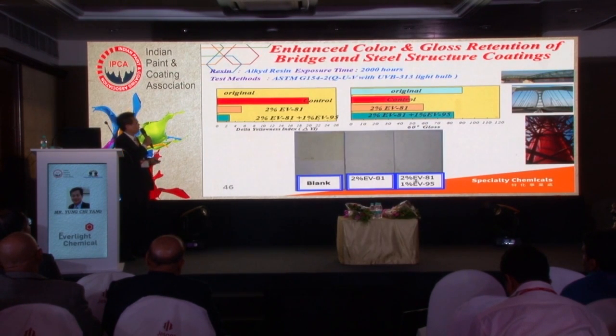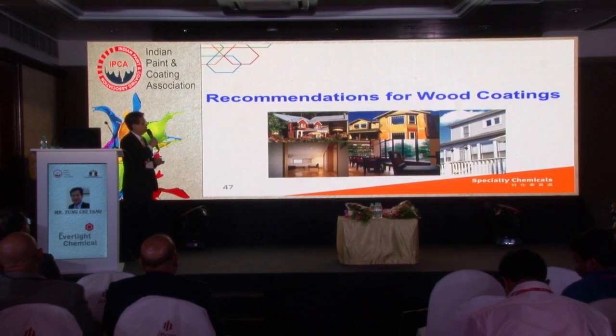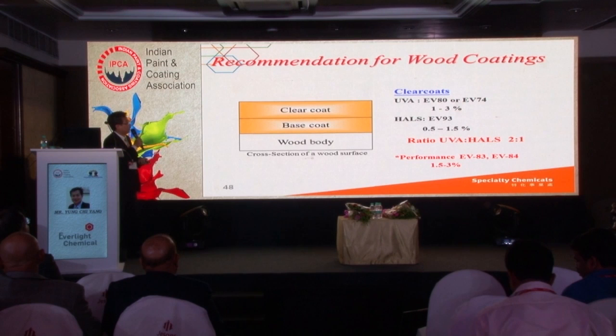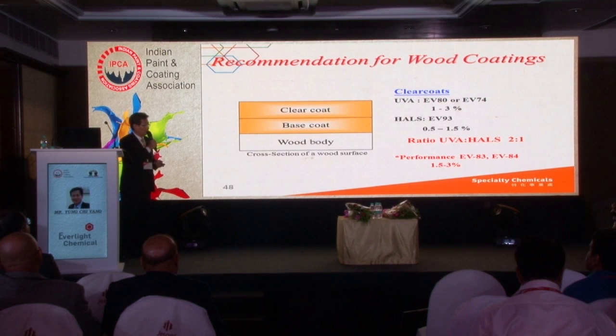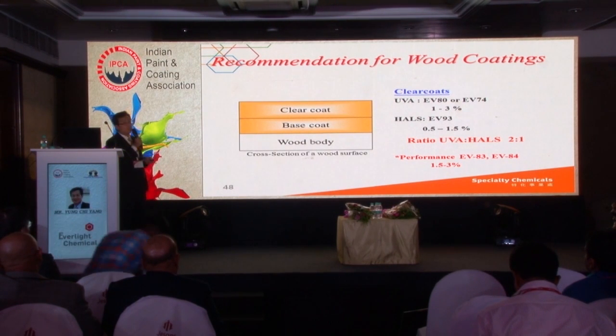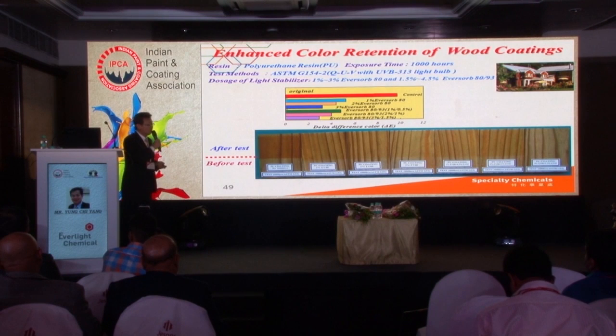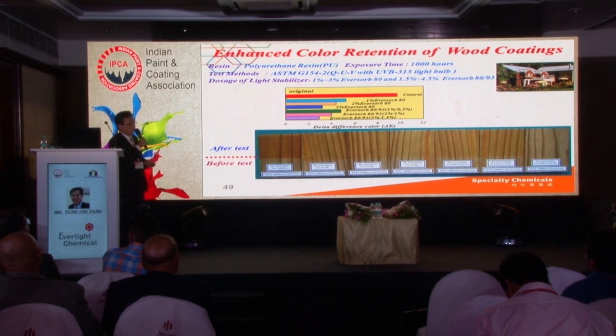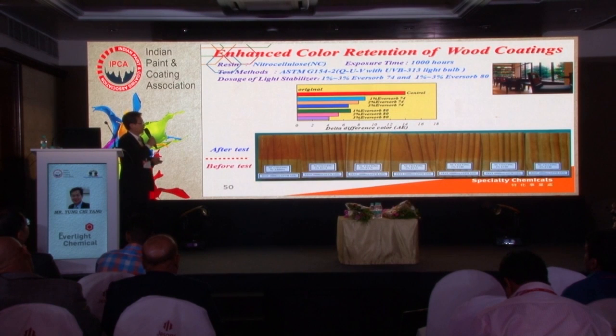So in this test, the two EV systems were tested for 2,000 hours, and you can see the 81 plus the 95 is good performance. And for wood coating, you can see the recommended ratio in the clear coating is 2:1. In the pigment it is 1:2. It's for the polyurethane for the wood coating, so you can see the good performance. The 80 plus the 93 can get the best performance. And this for the nitro series also can get the best performance.